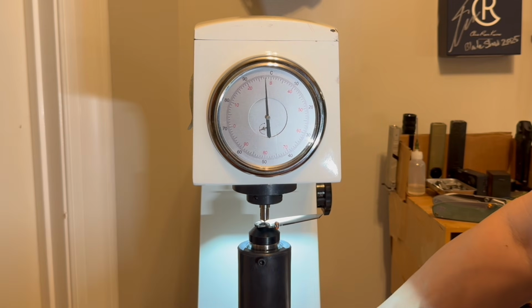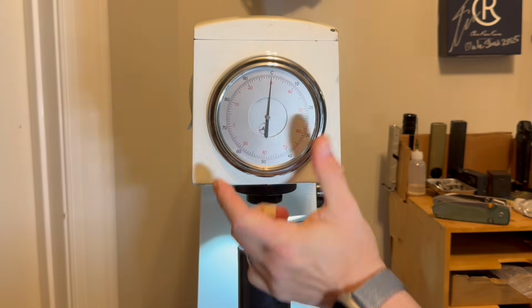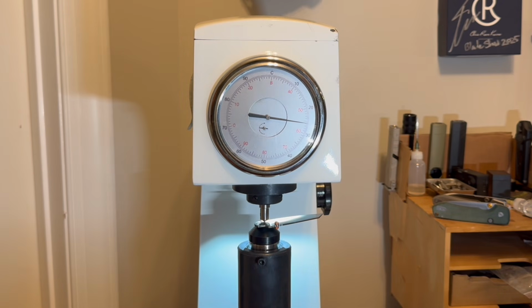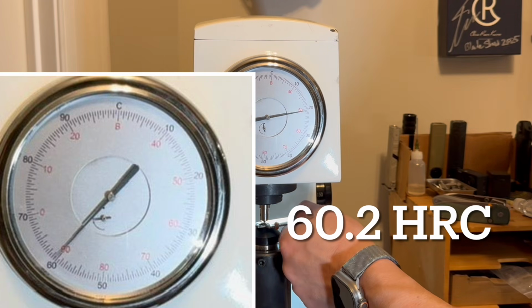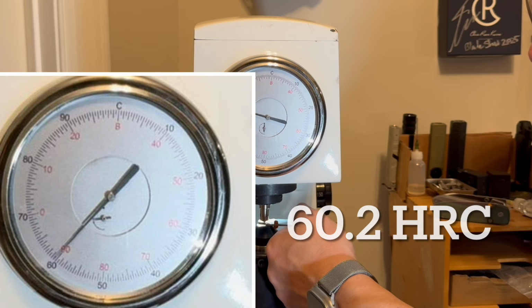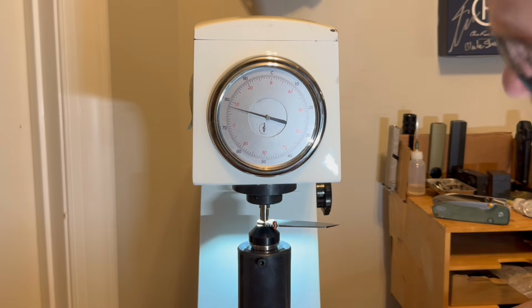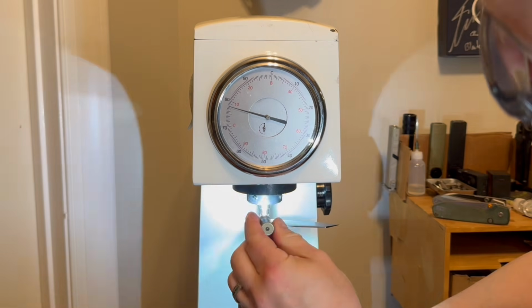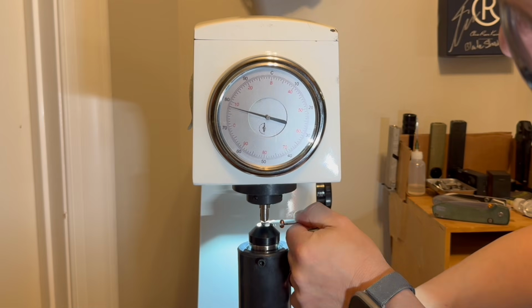So this is the uncoated blade from the parallel that I've had in my possession for at least a year or so. And the second poke at 60.2 HRC. So as you can see, pretty consistent repeatability here. We're getting good results. I'm poking it the third time.